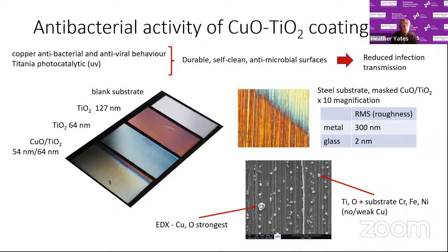Picture on the left shows the blank substrate for the metal and then with coatings of titanium on it. You can see there seems to be a red color when it's thickest and a blue color when it's thinner. Again, this is just due to interference effects from the light. And then a mixed coating of about roughly 100 nanometers in total.